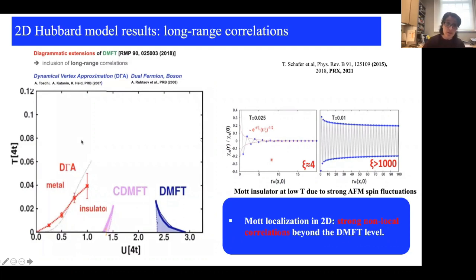And if you look at this picture, we see that once you take into account long-range interaction, we again observe a very strong suppression of the critical value of U at which the metal to insulator transition occurs. And as pointed out by the beautiful paper by Thomas Schaefer, this was taken from an earlier paper.